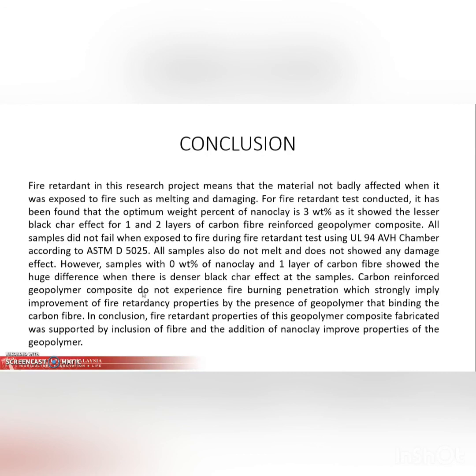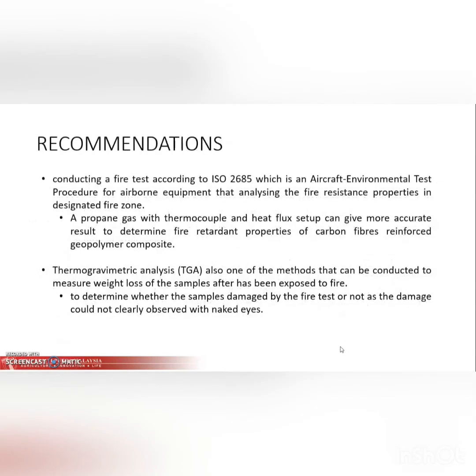The carbon fiber composite does not experience fire burning penetration, which strongly implies the improvement of fire retardancy properties by the presence of geopolymer that binds the carbon fiber. So in conclusion, the fire retardant properties of this fabricated geopolymer composite were supported by the inclusion of fibers and the addition of nanoclay that improves the properties of the geopolymer.